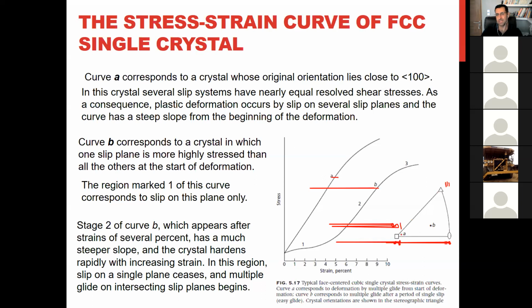For example, when I say A is here, it means we are applying load in the direction of 0, 0, 1, this direction. If I am here, I am applying load in this direction, or if I am here, in this direction. We are just comparing these two directions. It means one of them is close to 0, 0, 1, and another is the middle between these three. It means none of these directions, but in a condition that can activate just one slip system, not several.